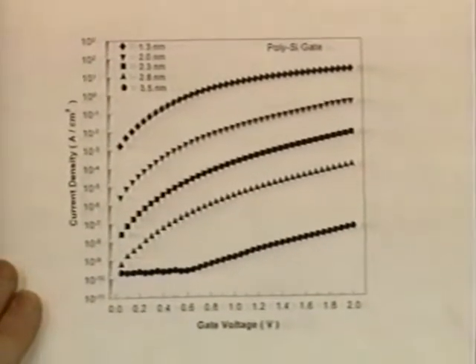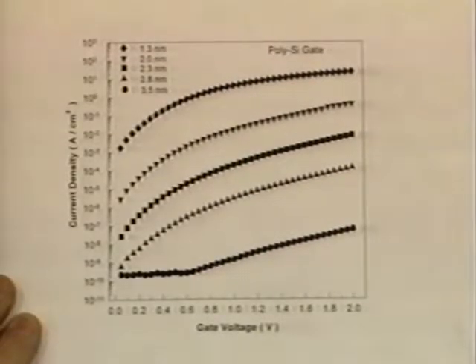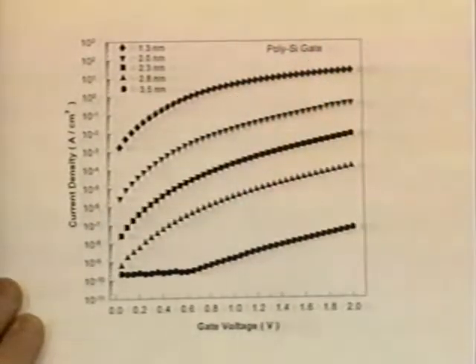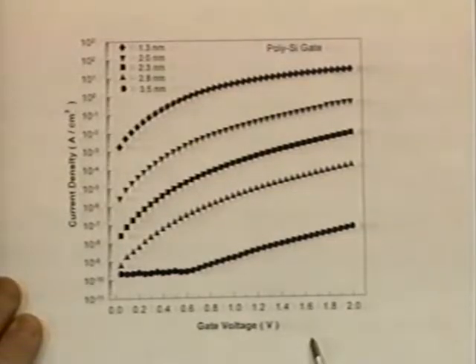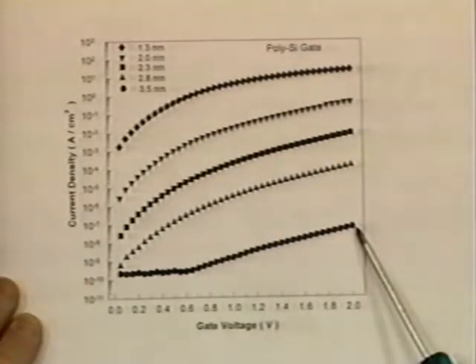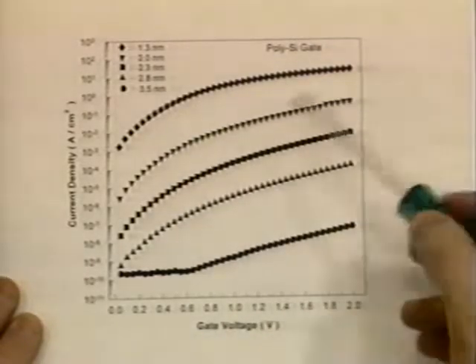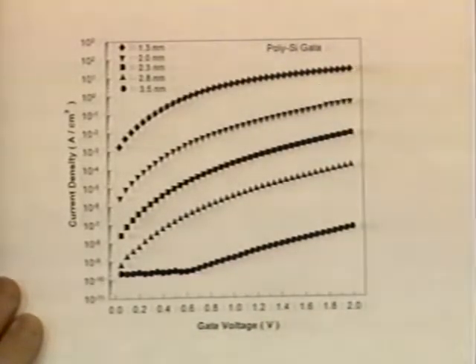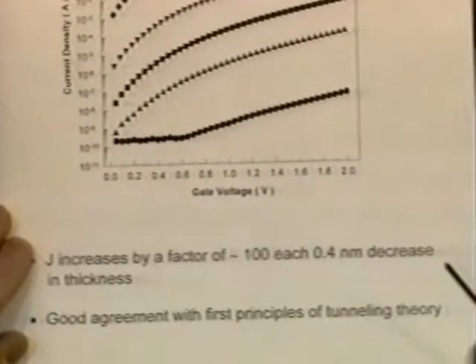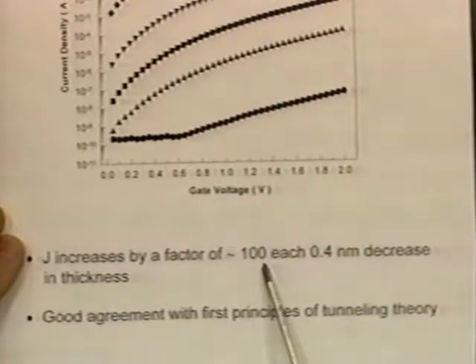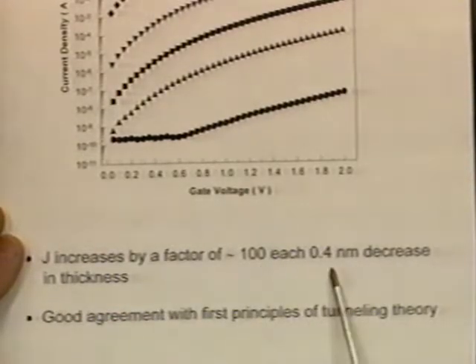The simplest way to characterize these devices is measuring current versus voltage. So what I'm showing here is for polycrystalline silicon gates, and for a while now I will be talking about the case where you inject from the substrate. This is a plot of current density, amps per square centimeter, versus gate voltage for the different thicknesses, for a thick oxide, for a thinner, and so on. And what you see, this ranges from 13 angstroms to 35 angstroms. Roughly speaking, the current increases by about a factor of 100 for every 4 angstrom decrease in thickness, which is in good agreement with tunneling theory.